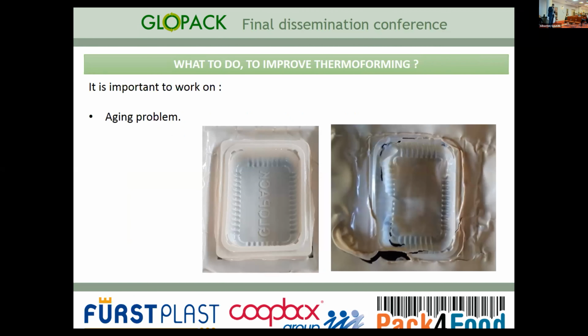The last one, which we already mentioned, is the aging problem. The aging problem for an industrial application is quite complicated, because if you buy some material, it's not possible to consider that you have to use or store it for two months at maximum. It's a very short time. And the problem is not only on the sheet, but also on the produced trays. So the aging problem should be solved to improve the processability of the material. For thermoforming, I finished.